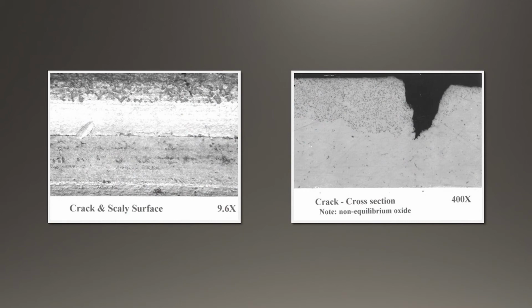Here's another example on the left. You can see a crack in the rod. And if you look at the right picture, you can see that there's a crack, but it looks completely different. And near the surface, there's some gray material. Well, that happens to be slag that got carried over from the molten metal into the cast bar, was on the surface, and that's what caused the crack that you see on the right.